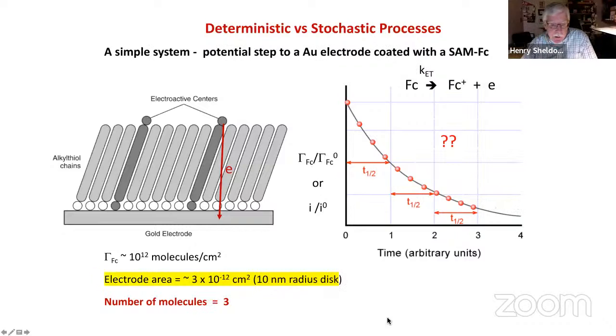Now let's do the same experiment. All we're going to do is change what I've highlighted in yellow here. Instead of using a macroscopic electrode, we're going to use a 10 nanometer radius disk. And now the area is 11 orders of magnitude smaller. This is doable. This is easy to make, a 10 nanometer disk. So this experiment is something you could go in the lab and really do. And now if you multiply the surface coverage by the area, it turns out there's only 3 ferrocene molecules sitting on the surface.